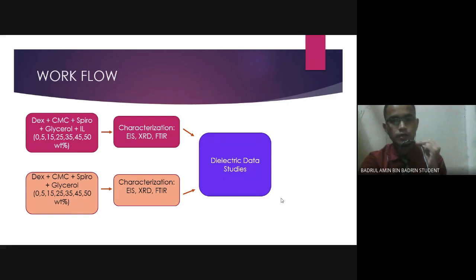So the highest conductivity obtained from the first system at the below of the diagram will be used in the second system with the addition of IL, which stands for ionic liquid. Both systems will undergo characterization, which are EIS, electrical impedance spectroscopy, XRD, and FTIR before going to dielectric data studies.